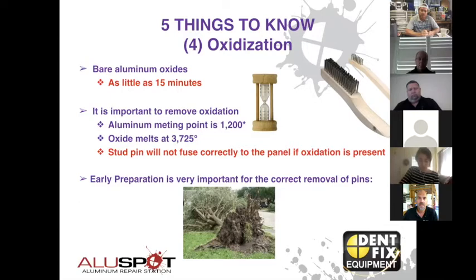This is really important. If you're not getting clean welds because that panel sat out for a few minutes, it's probably because there's too much oxidation. I've got a little video on that I can share as well. But it's important to remove all this oxidation. You're not going to burn it off when you do your heating, because oxide will melt at a much higher temperature than the actual aluminum will.